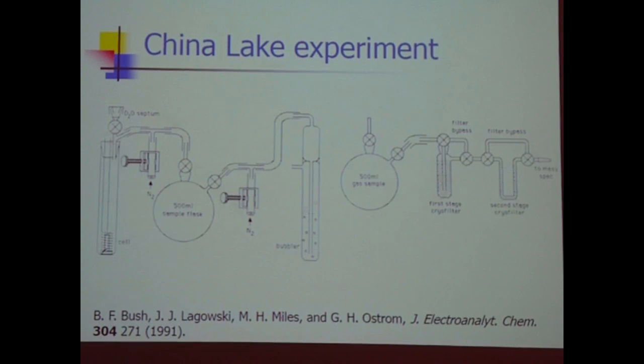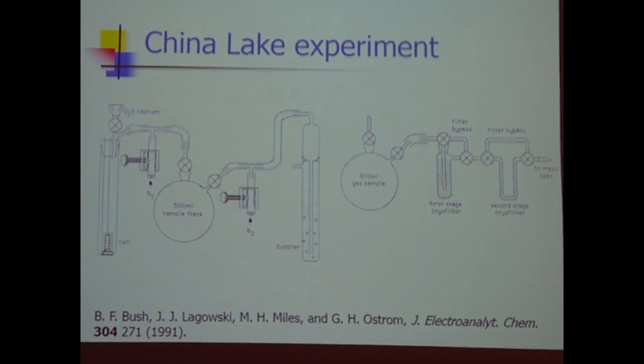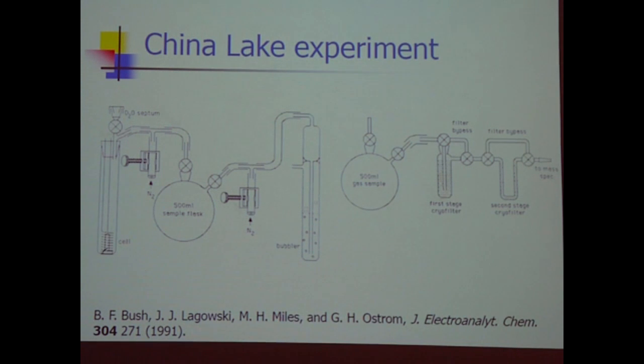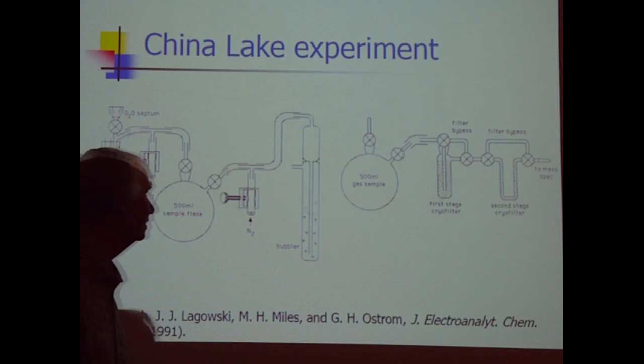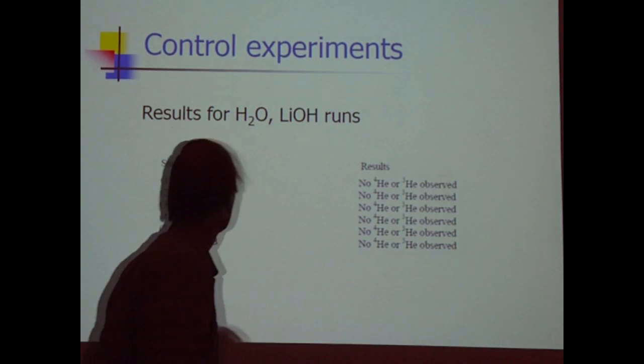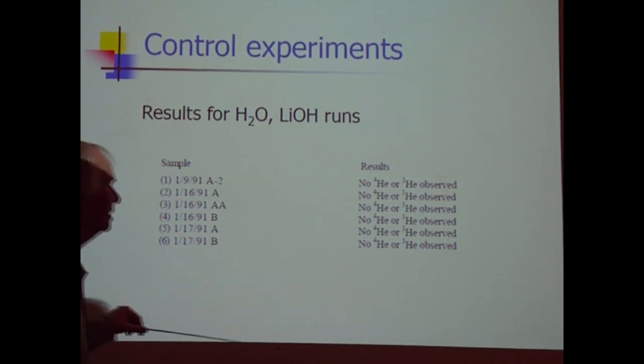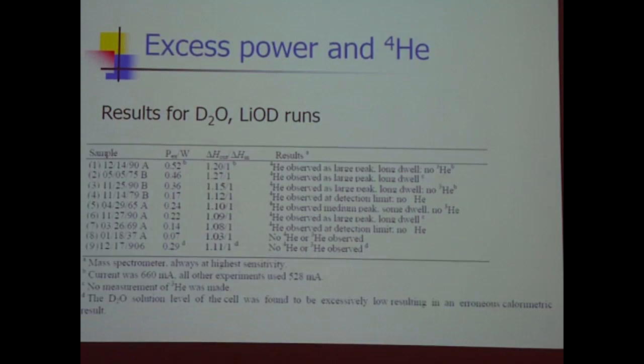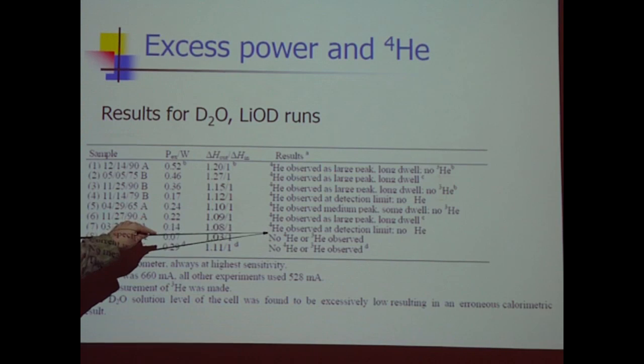So that's the problem. What's the response? Well, the response is to take some folks with expertise: Bush and Lagowski had expertise in helium-4 detection, and Mel Miles was an electrochemist, an expert in getting excess heat in cold fusion experiments. So they set up a cell, and they basically got gas samples, cryofilter, more cryofilters, you reduce the D2, you send it off to the mass spec, you do measurements, and what they found was for light water runs, they saw no excess heat, and they saw no helium-3 or helium-4. For heavy water runs, they saw excess heat, and in many cases they got helium-4.